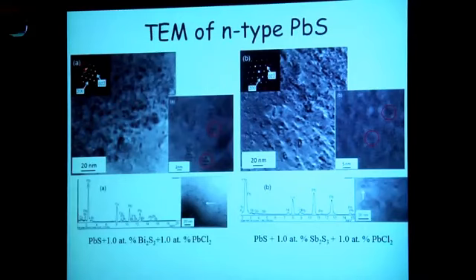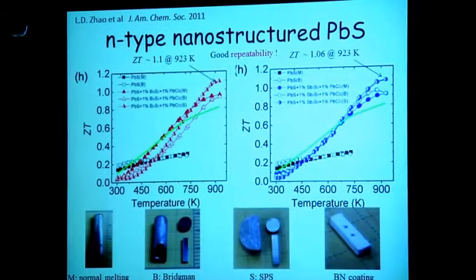And the diffraction pattern here, these are different crystallographic directions. It's single crystal. So these are all coherent. We can find the elements there, and we can see that the nanostructures are rich in antimony or bismuth. So again, we have successfully nanostructured lead sulfide and gotten very, very low thermal conductivities for that material.